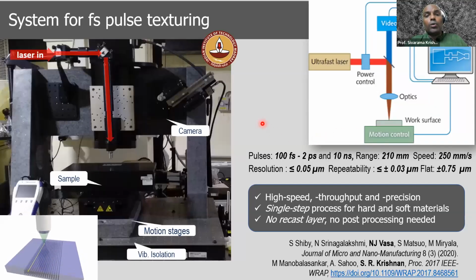Okay, now coming down to the specifics of laser matter interaction and micro machining in our lab and in our work group. Essentially, this is the gantry, a granite gantry, and the path of the laser beam going from the top left to the right towards the center of this setup and then going down is shown. And this train of laser pulses is focused onto a substrate using a microscope objective. And essentially what is then done is that the laser beam is held fixed in space, whereas the sample which is placed on these XYZ three-dimensional micrometer stages is translated.